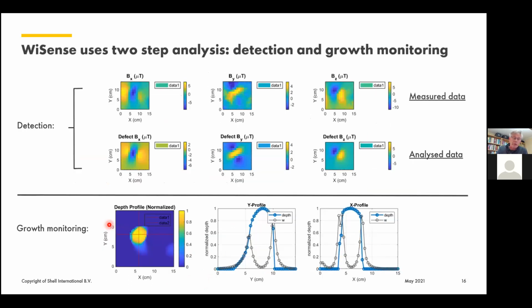And introducing the two algorithms that support the interpretation of the magnetic fields that the patch is picking up. What I said before, it is based on first subtracting the baseline. So what you measure on day 1, day 2 is taken as a baseline, and then you subtract it from all the subsequent measurements. Typically we collect with this system 1 measurement a day, at midnight, to reduce all sorts of temperature effects that might introduce small variations. So a very stable midnight measurement at a daily frequency. And that has proven for corrosion mechanisms to give you a nice measurement sequence that allows you to see a gradual change when the defect is growing.